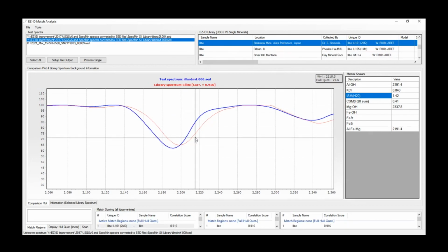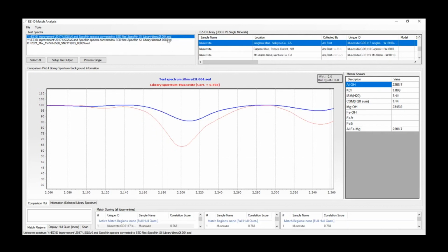So I don't know if you saw it on the screen or not, but the blue line has shifted quite a bit to the left. So if we look at our ALOH scalar, we've got a value of 2191.4 nanometers. Now remember, our very first illite was at 2208.7. So using this ALOH scalar here really gives you information about where your wavelength shift is occurring.